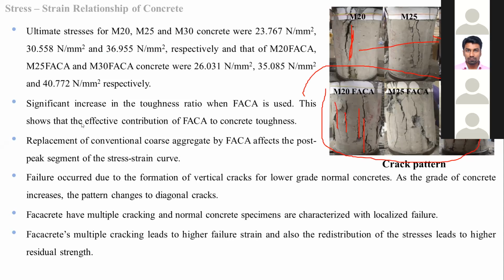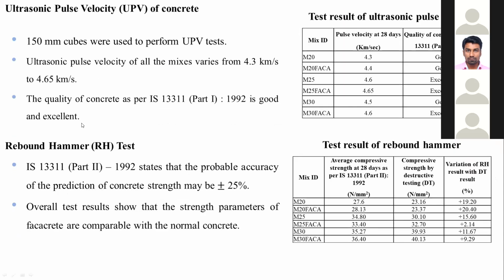Also, we found that the ultrasonic pulse velocity test and the rebound hammer test both come in line with the specified IS code limit. For the rebound hammer test, the variation of rebound hammer results with destructive testing, that is the experimental testing we have done, should not exceed plus or minus 25 as per IS code. As per our experiment, it comes within the limit of plus or minus 25. So this experiment validates that our research has gone in the correct way.